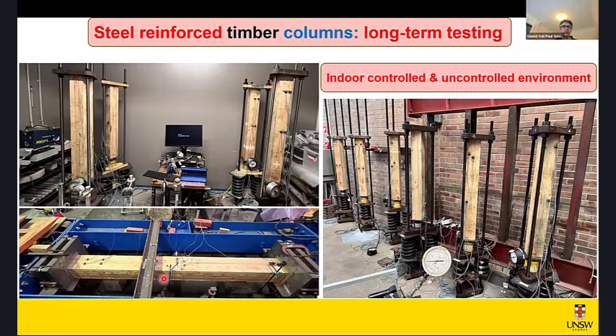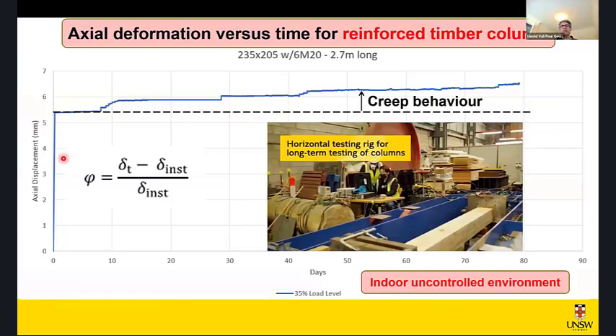We also did full-scale test on two columns. You see these are 2.4, and they were subjected to indoor uncontrolled environments. This type of graph is what we get from those long-term tests on the columns. So you could clearly see the creep behavior and the deformation, which is increasing over time. And we could get an additional like 25 to 35% increase in the shortening of the columns over time, over like 14 to 16 months, at the level of loading 30 to 35% of the peak load, which is, I would say, a very high level of the load on the service condition.